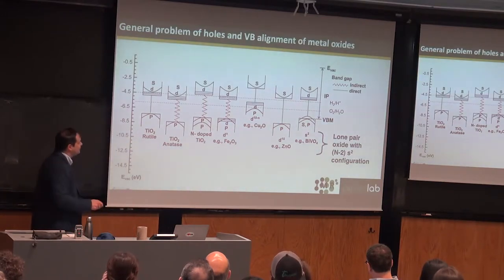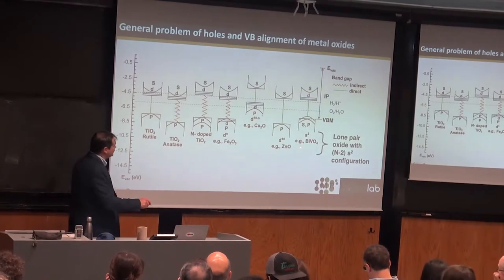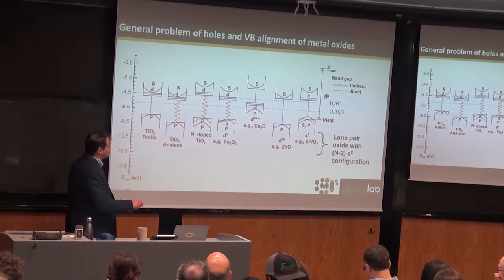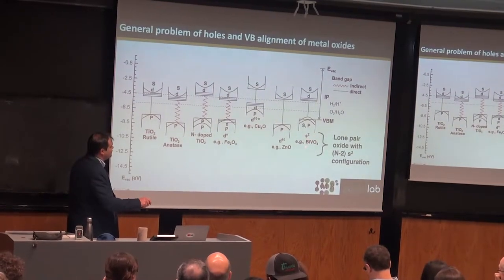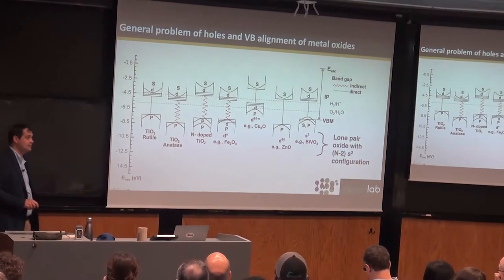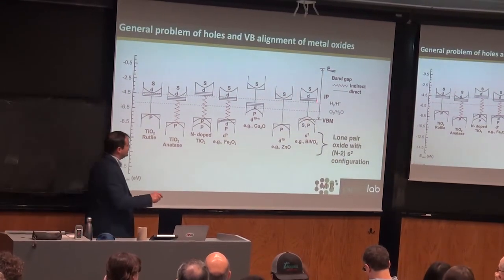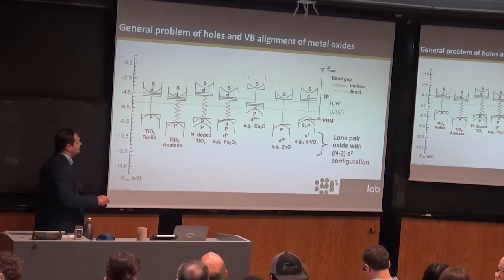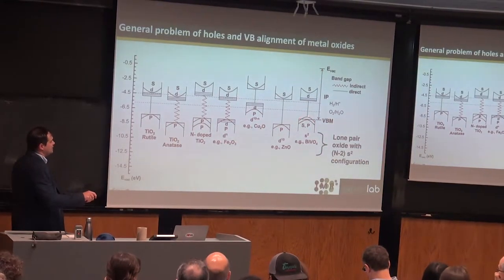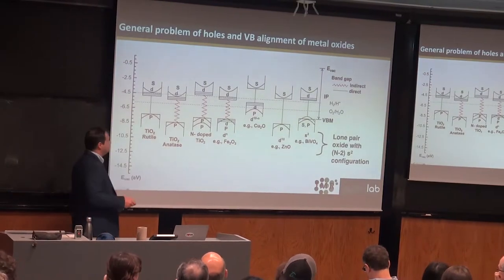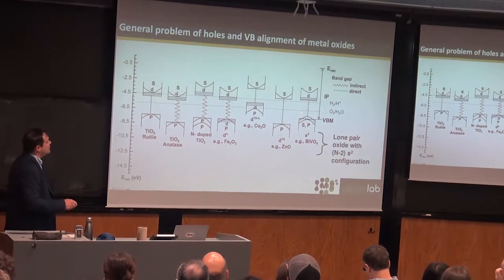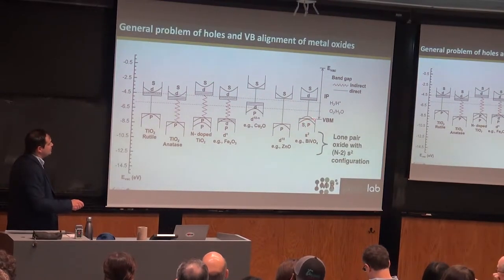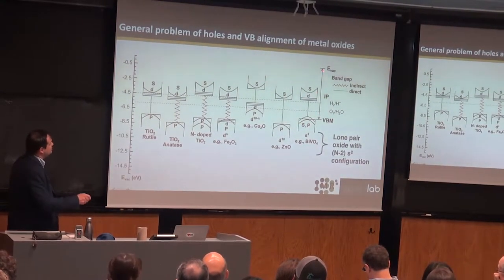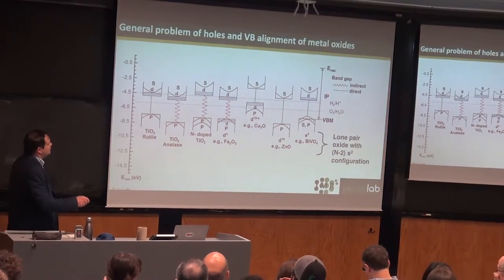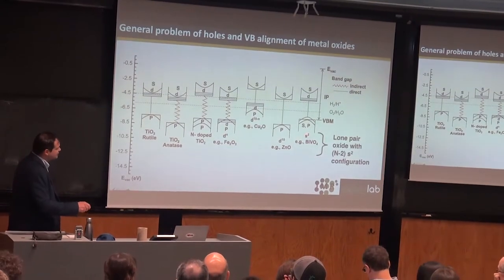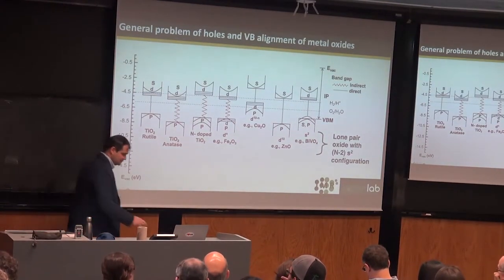And one promising candidate is to combine a system where you've got a d0, a bit like your titanium dioxide, with a system where there is a lone pair active post-transition metal ion. And that facilitates a situation where you get kind of more of a Goldilocks regime, where you have a direct band gap and you have s and p orbital mixing here. And s orbitals are good for more dispersive bands that translate into better mobility of your holes. And it gives you a way in which you can raise, through the metal hybridization, your ionization potential. So in this case, we're just interested in how we can engineer the ionization potential. And this is very promising, these lone pair oxides.